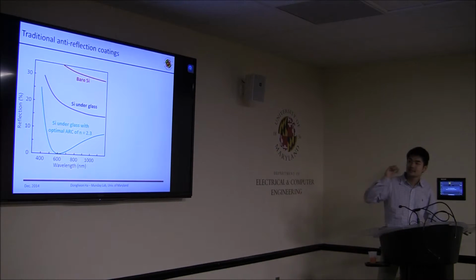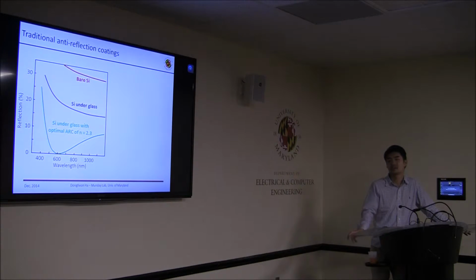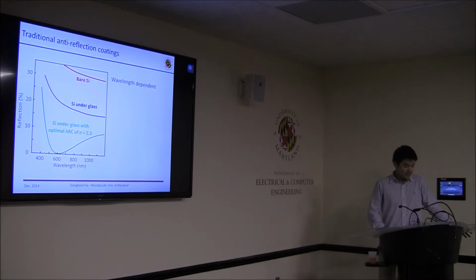However, when you add a simple glass slide on top of the silicon, we have less reflectance. That is because now we have a smaller index change from air to silicon, because the refractive index of glass is somewhere between air and silicon. However, if we apply the optimal conditions, we can further minimize the reflectance, and at a wavelength of 600 nanometers, it is around 0%. This is really good.